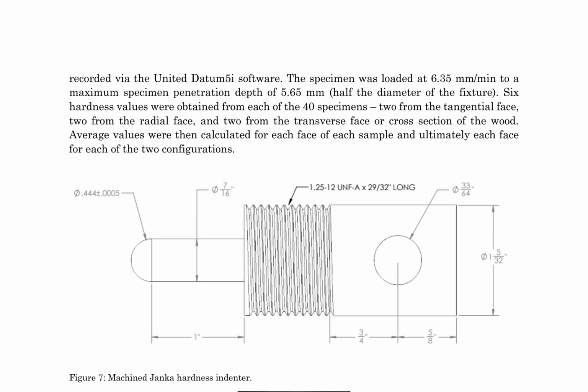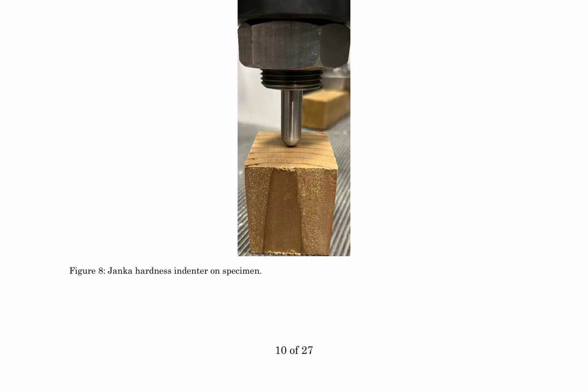6 hardness values were obtained from each of the 40 specimens, with 2 measurements taken from the tangential, radial, and transverse faces. Average hardness values were calculated for each face of each sample and then for each face of the 2 configurations. Figures 7 and 8 showcase the machined Janka hardness indenter and its placement on the specimen during testing. This setup allows for precise measurement of the material's hardness in different orientations, providing insights into its anisotropic behavior and